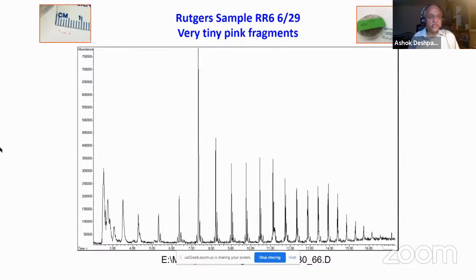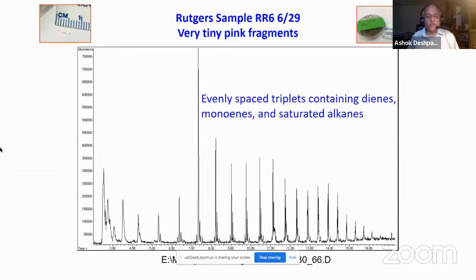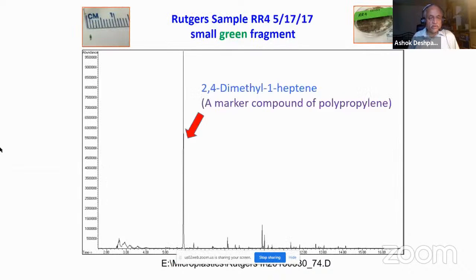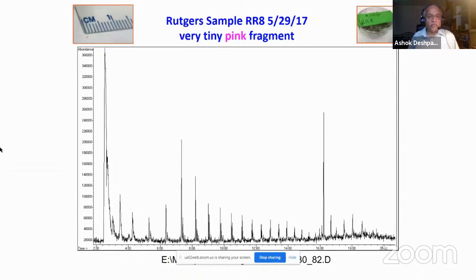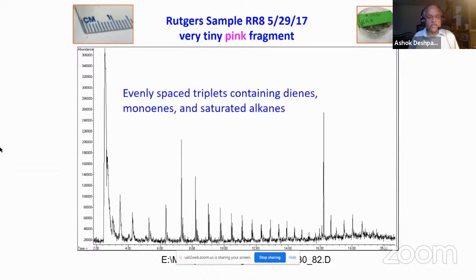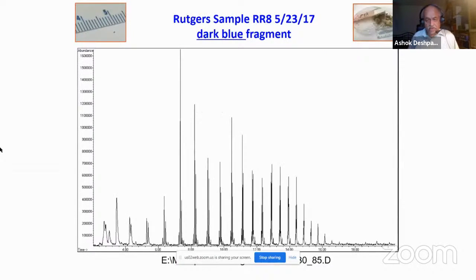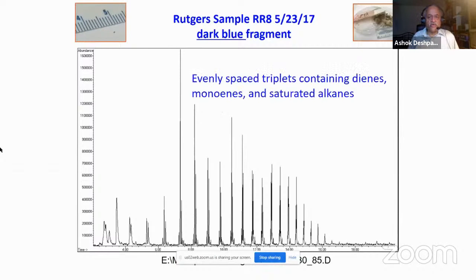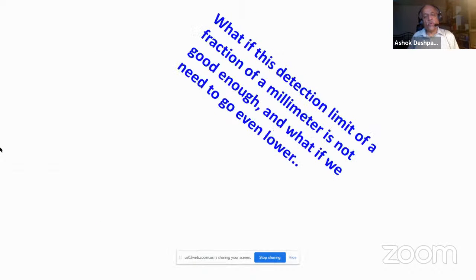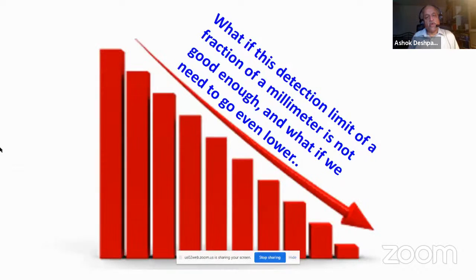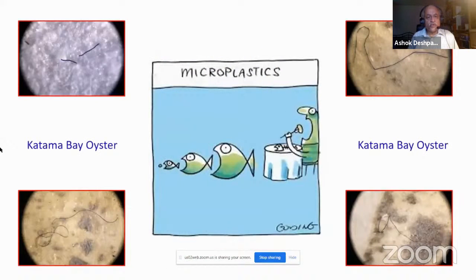So as you can see on the left-hand side, there are tiny pink fragments. We found evenly spaced triplets, which is indicative of polyethylene. This is another green fragment. We found it has a marker peak of polypropylene. This additional small tiny pink fragment had a signature of polyethylene, I'm sorry. And this dark blue fragment has signature of polyethylene. So the next question is, what if this detection limit of a fraction of a millimeter is not good enough? And what if we need to go even lower? So this question comes into picture when we work on small animals like oysters or other shellfish.